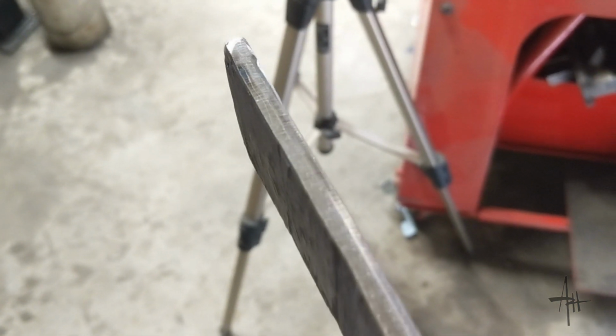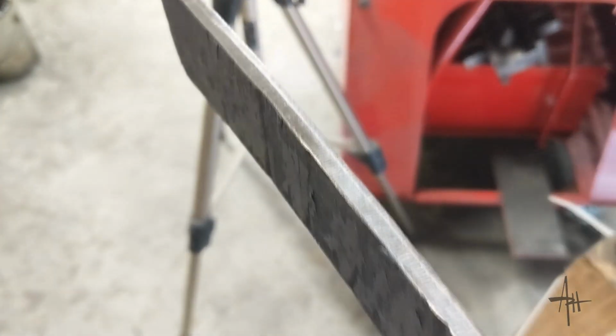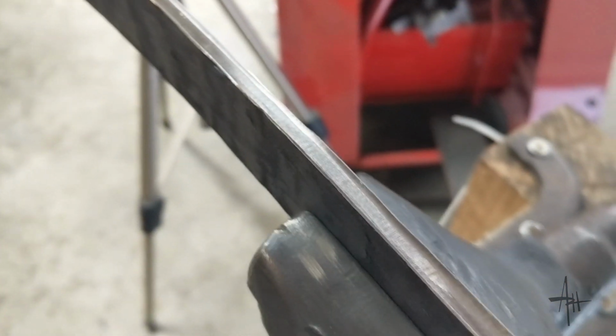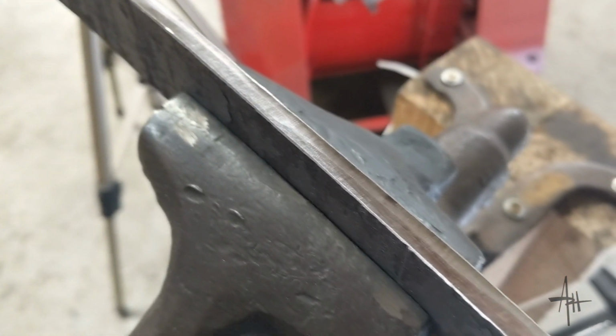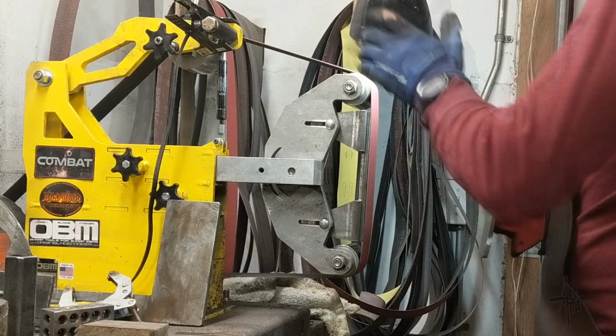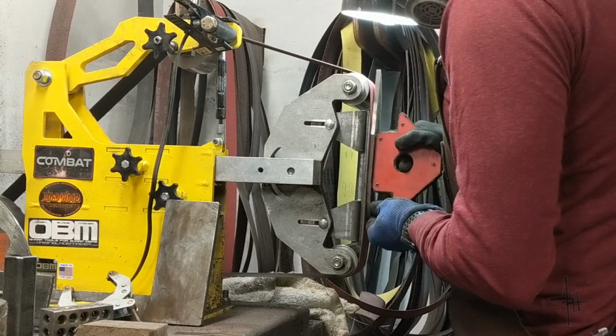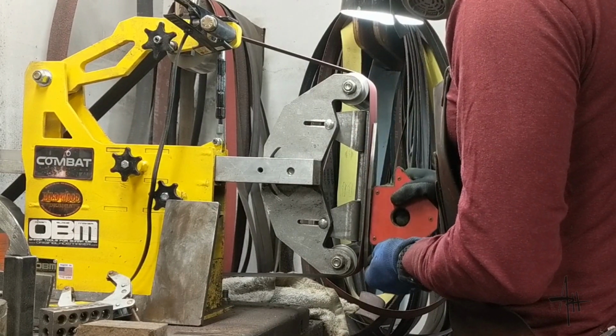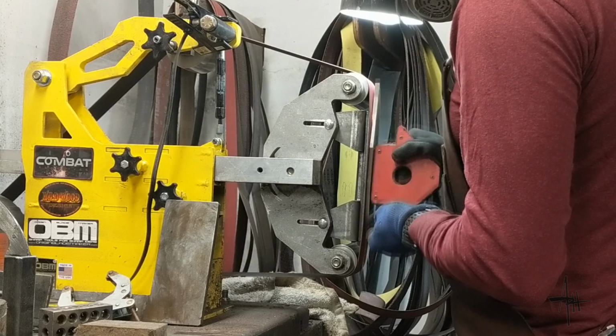Obviously, once you take it to the ferric chloride etch, it won't even touch the stainless, so it stays really nice and white, and then that high carbon core gets really dark. You also can kind of start to see where some of the carbon migration occurred between the high carbon and the stainless, and it creates this really cool hazy effect.